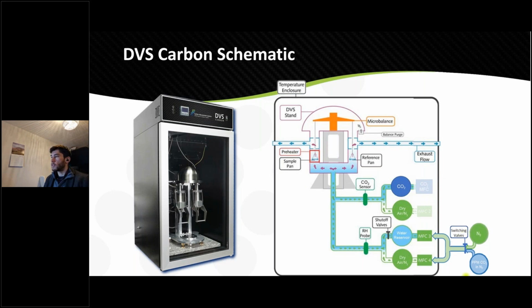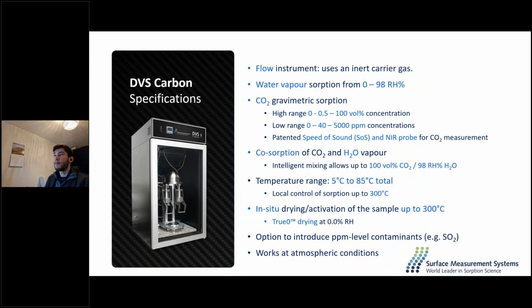There is also on the side a switching valve here, which allows the carrier gas to be switched from either pure nitrogen in this case, or a carrier gas with a pre-calibrated concentration of CO2. What this means is that different concentrations of CO2 are accessible. There is a high concentration from 0 to, I think it's best if I go to the next slide. So two concentrations can be accessed.